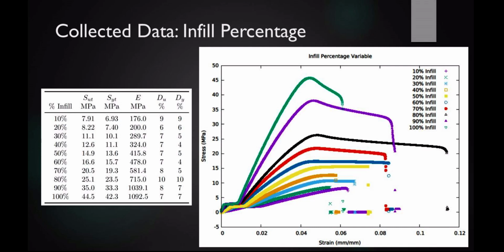For 70% and 80%, we see really good ductility, really good toughness, that they're really able to deform and continue carrying a high load for the entire time, right up until they fail at the last minute there. 90%, the same story, but you have a significantly higher ultimate and yield strength because the curve is just able to shoot up faster. You have more material there. 100%, again, it shoots up faster, but it fails earlier.